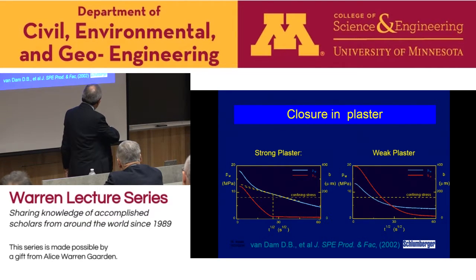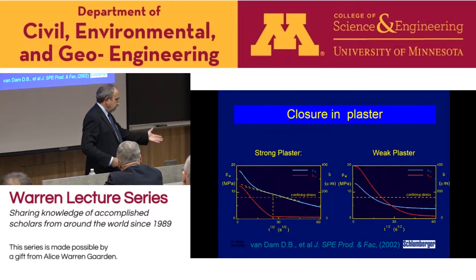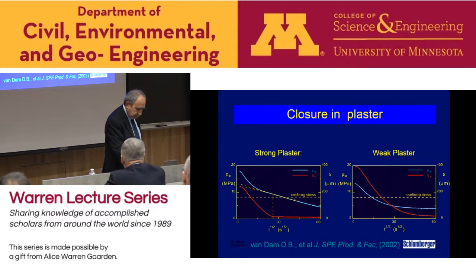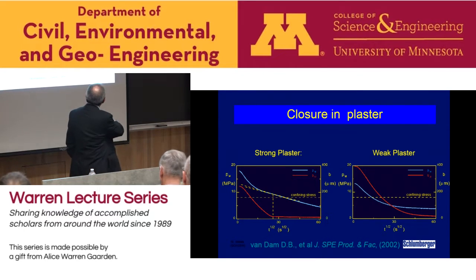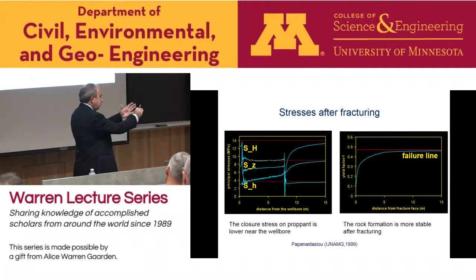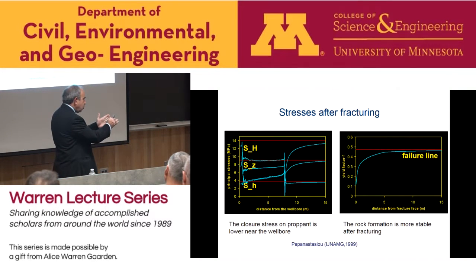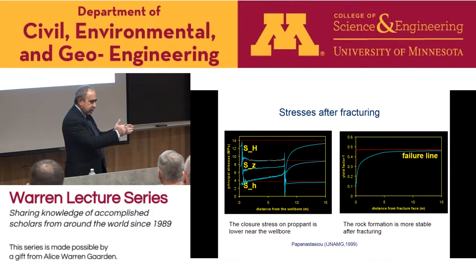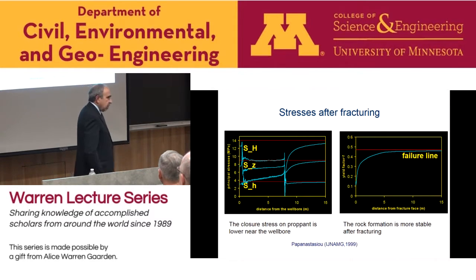But these operations for the calibration of hydraulic fracturing are carried out in short fractures. So we create a fracture of 2 to 3 meters long, and then we allow it to fracture to calibrate the operations. We change also the stresses after fracturing in weak rocks. We do hydraulic fracturing. We allow the fracture to close on the proppant. Proppant is the material, like sand, that is keeping the fractures open. And after we allow it to close, we have all the stress redistribution.